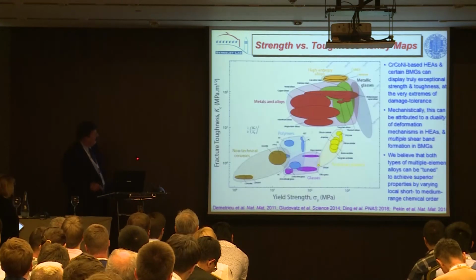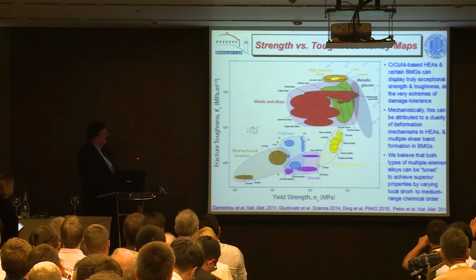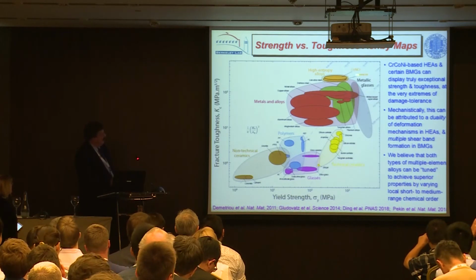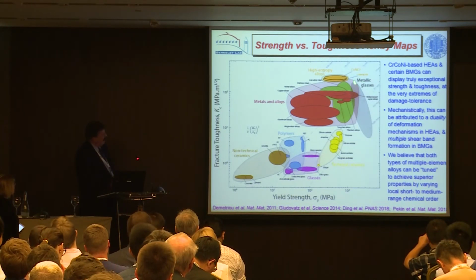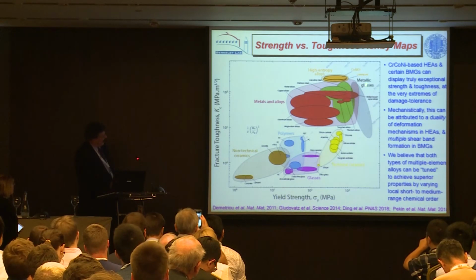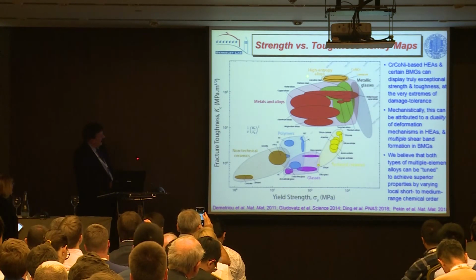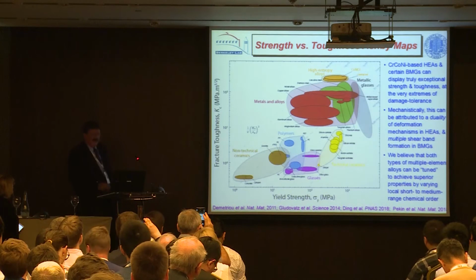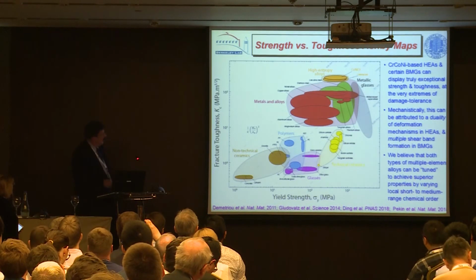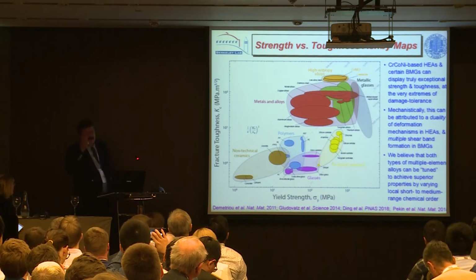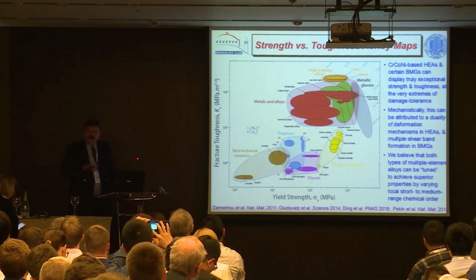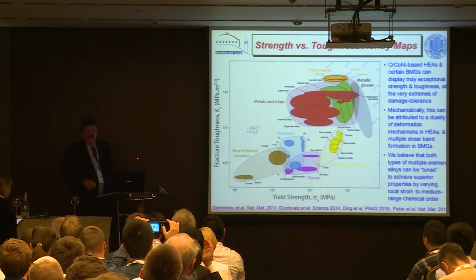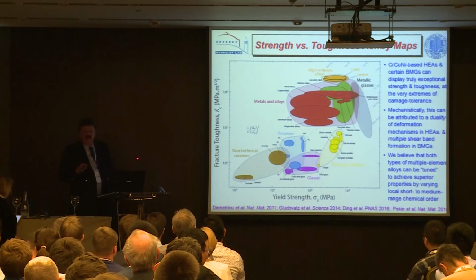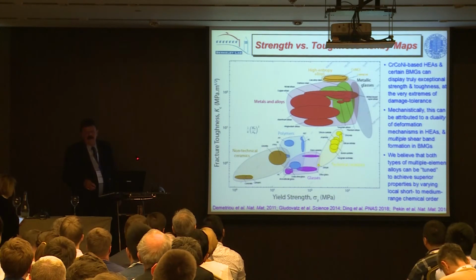So let me finish just by showing you this plot again. These multi-element metallic alloys have a remarkable damage tolerance. The glasses have the highest strength. The high-entropy alloys seem to have the highest toughness. These are the cobalt chrome nickel alloys. And we think in both these cases the notion of local, short to medium range order has a very important effect on the development of these materials.